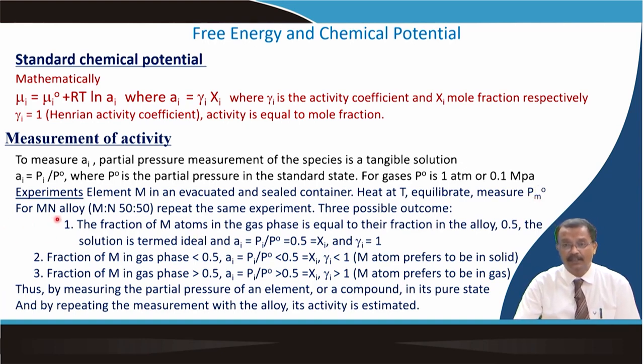Now, you consider an alloy of M and N, say 50-50, and repeat the same experiment. You can have three possible outcomes. The first outcome is that the fraction of M in the gas phase is equal to its fraction in the alloy, which was 0.5. Then the solution is termed ideal. So a_i is p_i by P0, that is 0.5, equal to the mole fraction, and gamma is equal to 1. Likewise, the fraction of M in the gas phase could be less than 0.5, so your gamma i is less than 1. That means physically that the M atom prefers to be in the solid. And when gamma i is more than 1, the M atom prefers to be in the gaseous state.